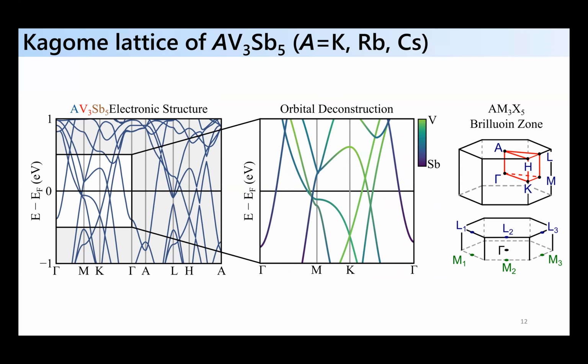But if you zoom in here, I want to try and highlight a few features, right? So if you look at the endpoint, first of all, you see there's a series of these Van Hove or saddle points, which are close to the Fermi level, okay, from this sort of DFT calculation. And these are all derived from the vanadium orbitals that comprise the kagome network, okay? So it's a kagome metal. All the states at the Fermi level, with the exception of this electron-like pocket at gamma, come from vanadium ions.